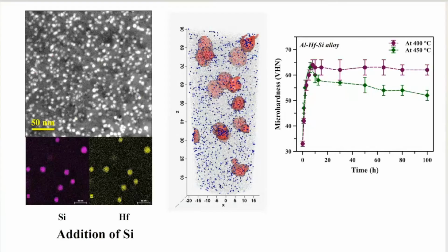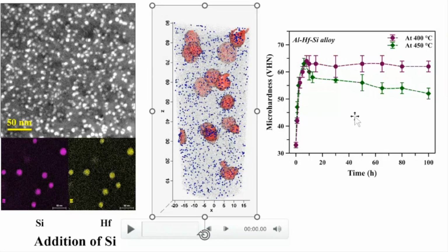For aluminum hafnium, if you add silicon, cellular precipitation can be stopped. What you see on the left-hand portion of the slide is a hafnium alloy with a silicon addition. You can see the ordered precipitates at the bottom with the silicon map and hafnium map, and it is really a good dispersion. On the right-hand side, you can see the microhardness, and you see that hardness at 450 and 400 degrees centigrade is pretty stable over 100 hours. That means this is like gamma prime in nickel-based superalloys. This is a very stable precipitate.